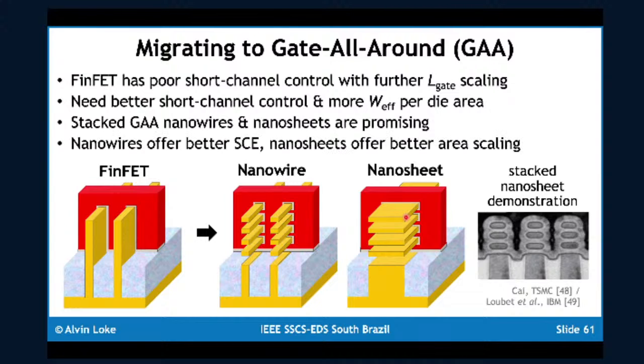Now, the nanowires, by virtue of the gate wrapped around in much closer proximity to every point in the nanowire, is going to give you better short channel effects. However, you're going to get better area scaling with nanosheets. So, just from a simple crystal ball opinion here, I do not expect nanowires to see light of day. We will probably migrate directly to nanosheets, even because of the effective width scaling proposition.